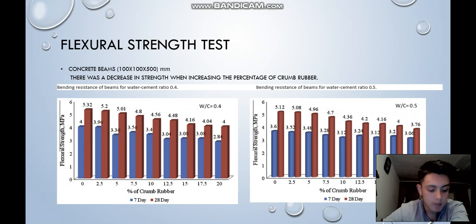Flexural strength test. In these tables we can observe the resistance to bending in megapascals against the percentage of tire dust for the water cement ratios of 0.4 and 0.5. For the test, two samples were taken, one at 7 days and the other at 28. It was noted that the lower the amount of tire powder, the greater the resistance to bending. It was also noted that the 28 day samples had greater resistance, for water cement ratios of 0.4 and 0.5.